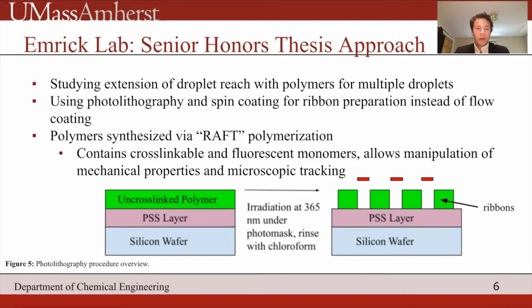And so the polymers are synthesized using RAFT polymerization, which is a controlled radical polymerization process. The first polymer that we were working with contained cross-linkable and fluorescent monomers, allowing for the manipulation of mechanical properties via the cross-linkable component and microscopic tracking via the fluorescent component. So, as I previously mentioned, prior ribbon making using flow coating was limited in its scalability, and so we are using photolithography, which is typically used in the synthesis of computer chips, to scale this process up.